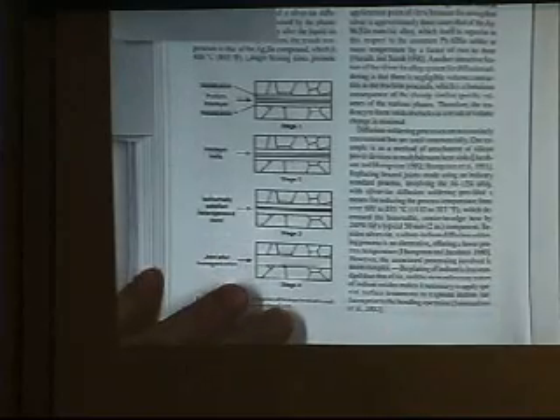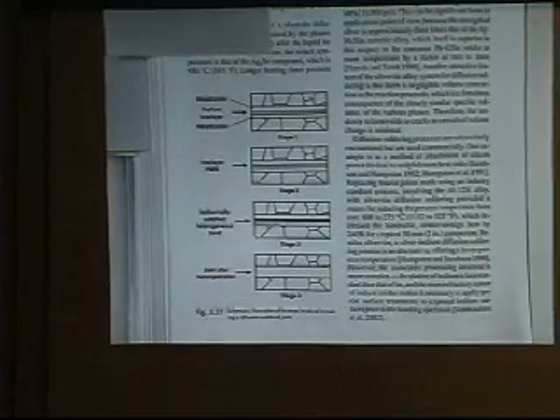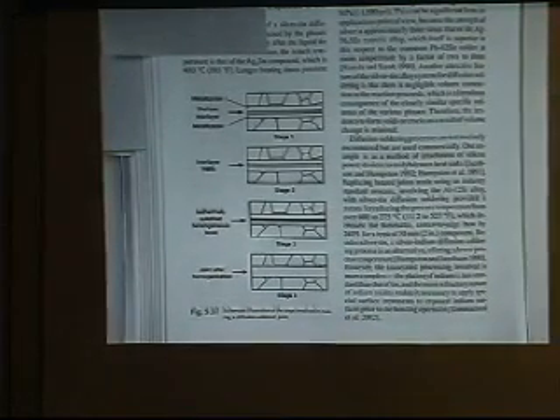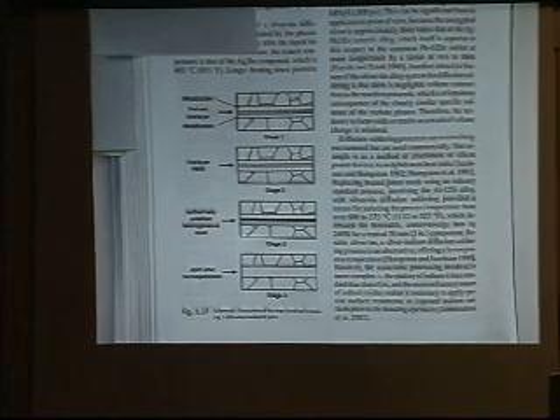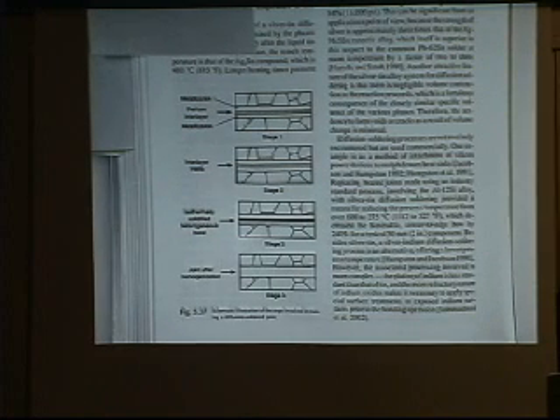So they're actually forming a low temperature transient liquid phase diffusion bond. Back when we published this in the early 90s, we called it low temperature TLP. They call it diffusion bonding. And lo and behold, this is their little schematic of how the process works. It's not all that different than the schematic that I showed you of diffusion bonding. Well, in fact, where did they steal that from?